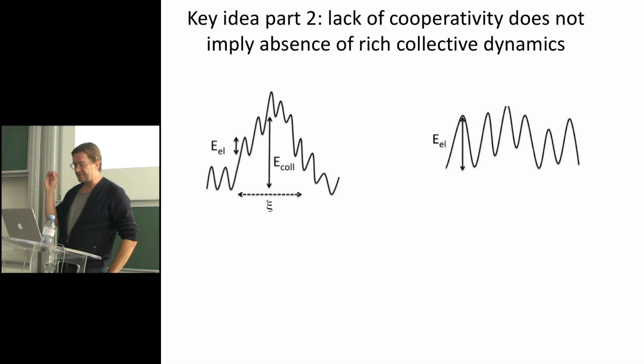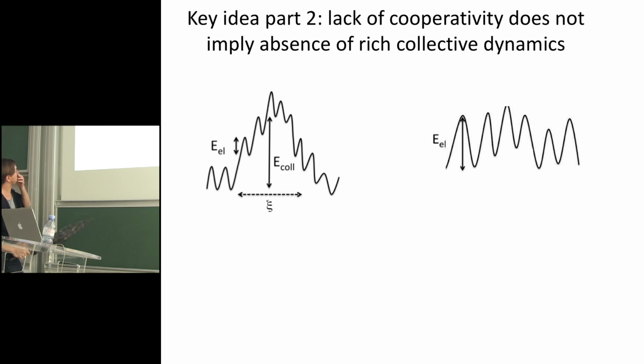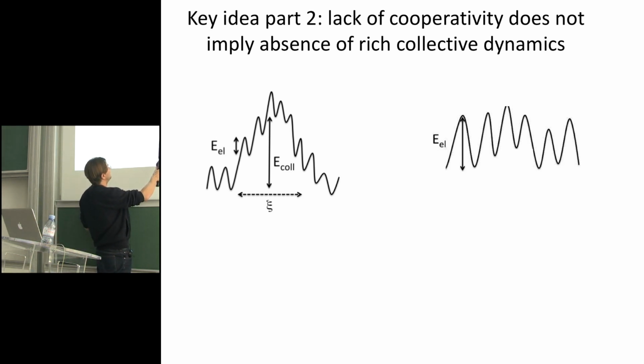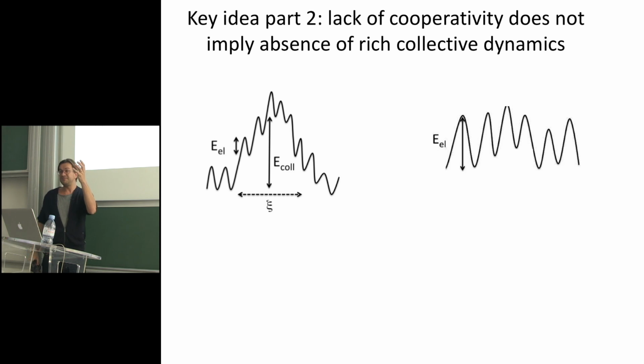So maybe the take-home message is that many theorists in the field think about collective dynamics and barriers being really controlled by the same phenomenon. Here, what I'm showing you is that even though the activation energy is just controlled by elementary excitations, as in those models, you can still have a very rich, correlated dynamics.